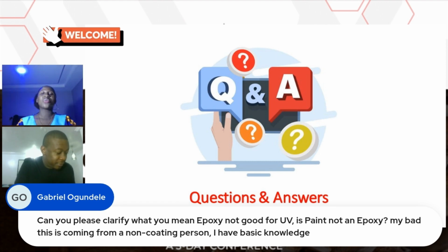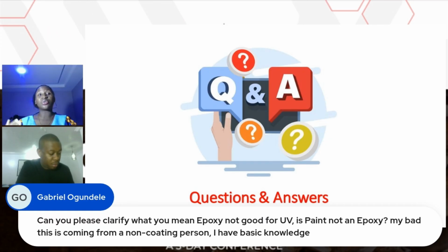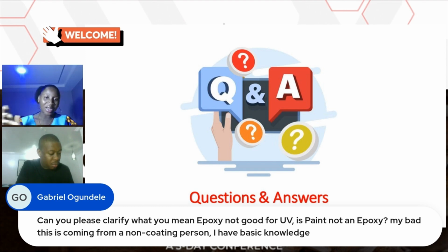So when we say epoxy is not good for UV, you may want to take your time to actually study what the epoxy system is. Yes, they are very excellent corrosion resistant products. They are durable. They are very flexible. When I mean flexible, they are very compatible with other top coats. But then it has a downside, and that downside is that it tends to chalk on exposure to UV.